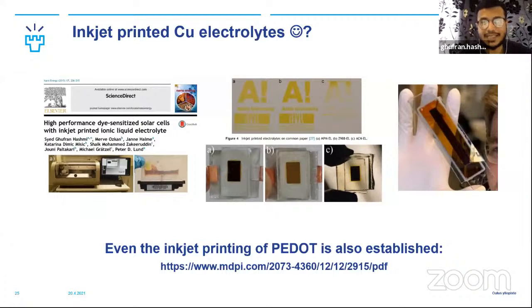And it suppresses all this non-active area, as you can see on the right side of the picture, where a lot of non-active area is induced as a result of drilling holes where you have to inject the electrolyte. So that affects the overall cell resistance. If you directly print on this titanium electrode, all this unnecessary non-active area can be significantly suppressed. And we showed that if you minimize this non-active area, then the performance can be improved by reducing the overall cell resistance.